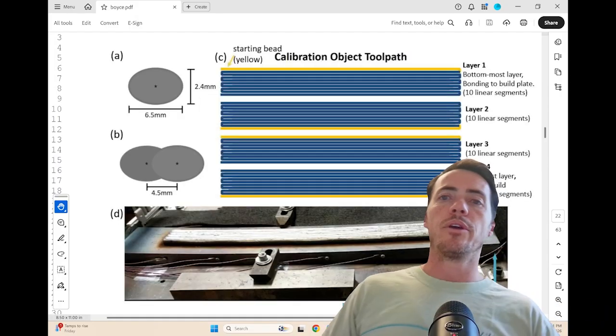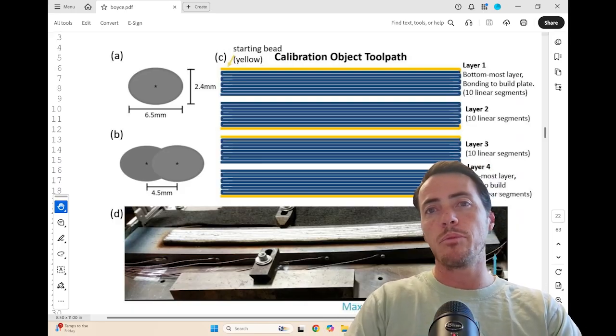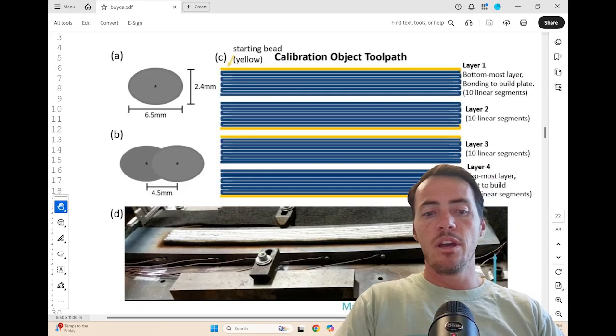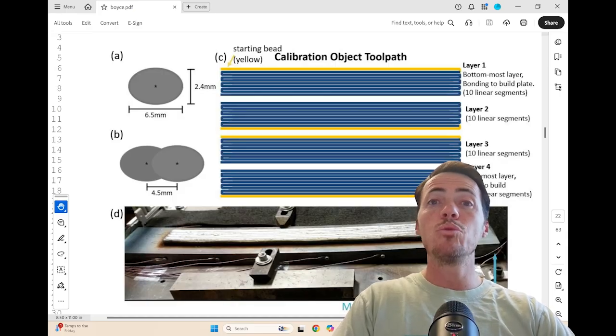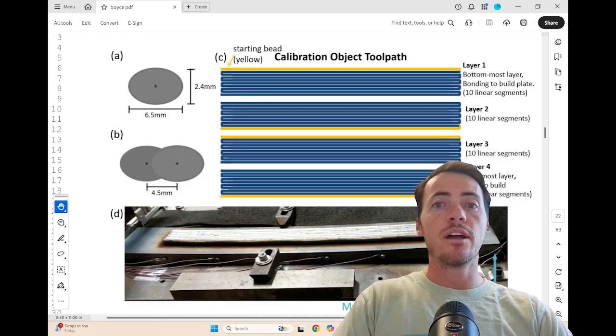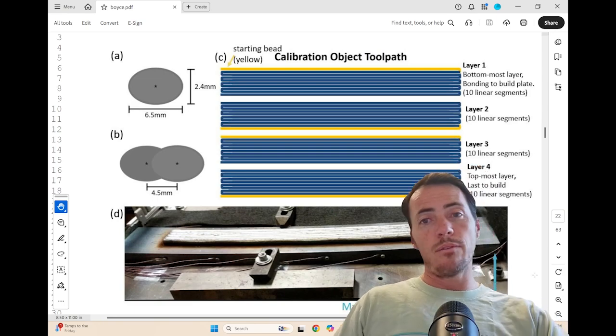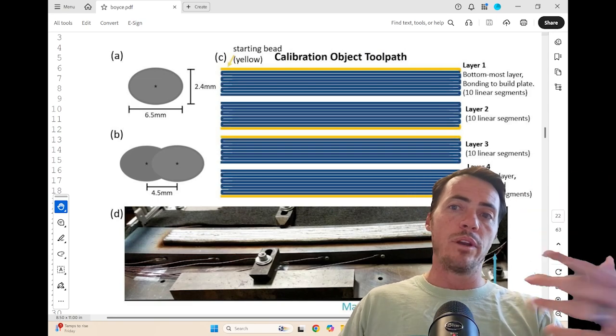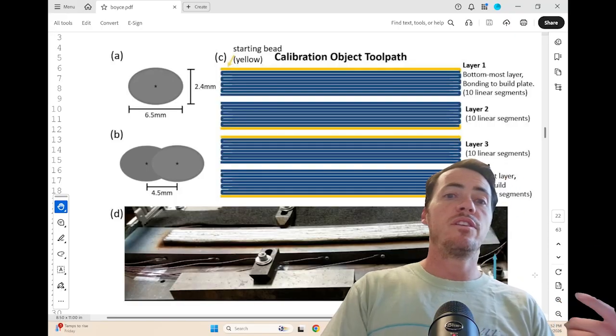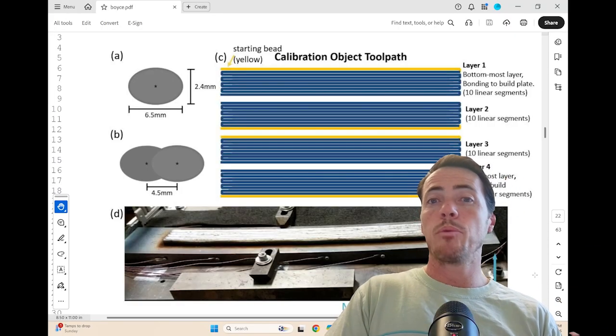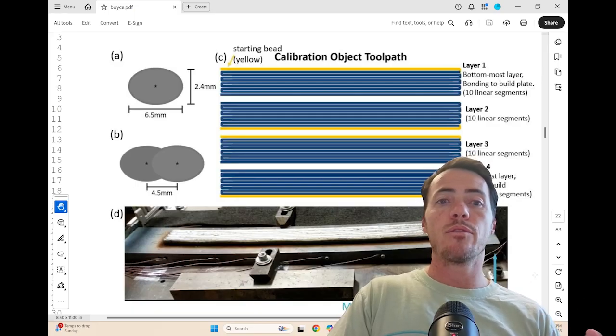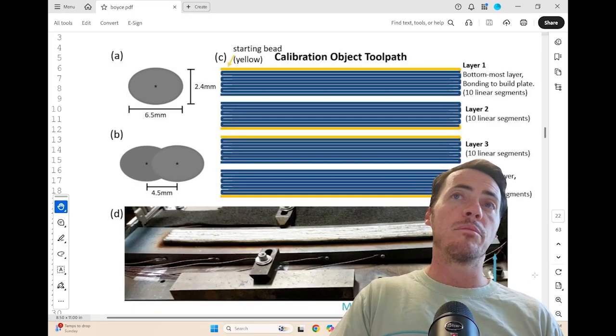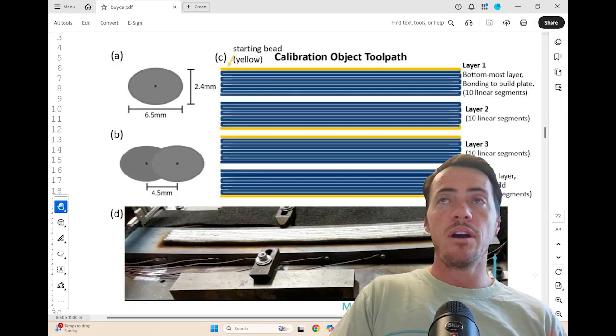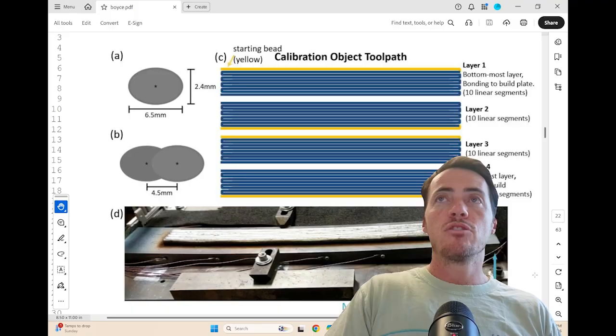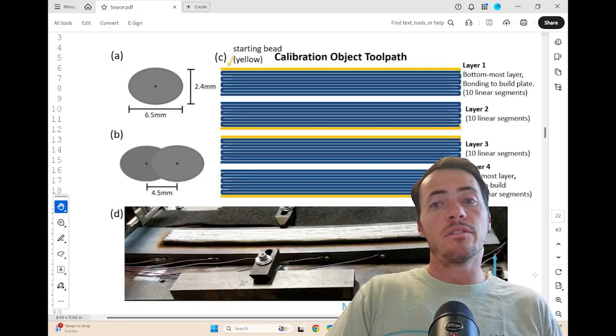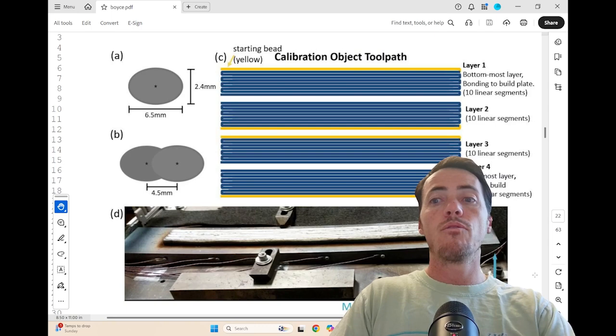We'll jump down here to the calibration object toolpath just to illustrate the difference between the calibration specimen and the challenge specimen. They're not just different geometries, they're different tool paths, and that makes a big difference. For example, in this calibration toolpath example, the torch travels really long distances between when it returns back to its original location. However, in the challenge specimen, that toolpath was much shorter, and it produced dramatically different thermal accumulation and cooling behavior. And that's important because we know that residual stress should be highly sensitive to thermal history, and we've changed it. So by changing the toolpath, the researchers here have created what is going to be a much more challenging test for predictive models.